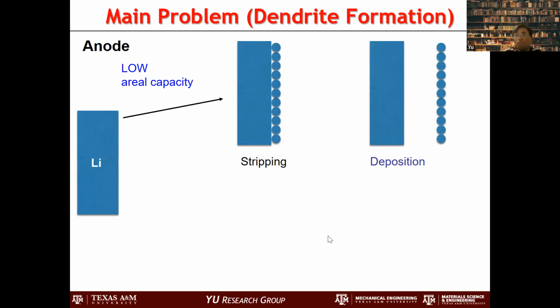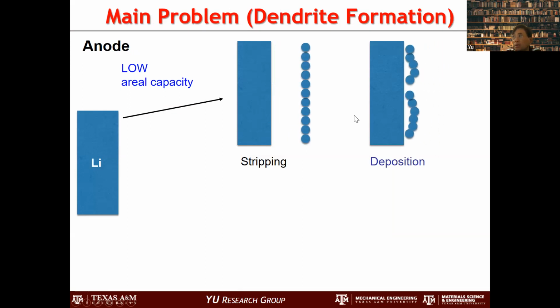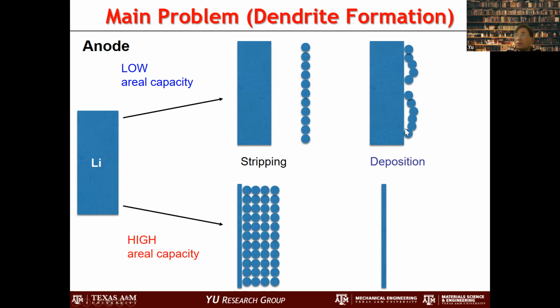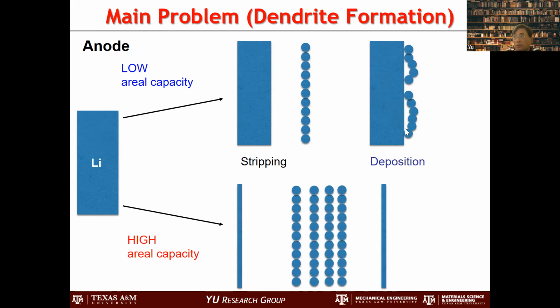Another problem is that when lithium is stripped and deposited, it doesn't return to its initial position, so it becomes like that. When we have a large amount of material stripped and deposited, this really becomes problematic. This one is not that problematic because it's not that sharp, but this one is pretty sharp, and it pokes through the separator, and then you have a short circuit and you catch fire. This becomes really problematic, so we want to avoid that.